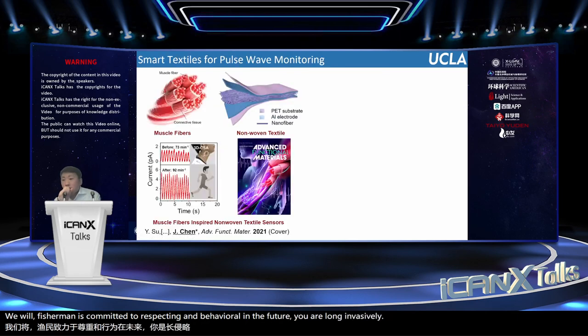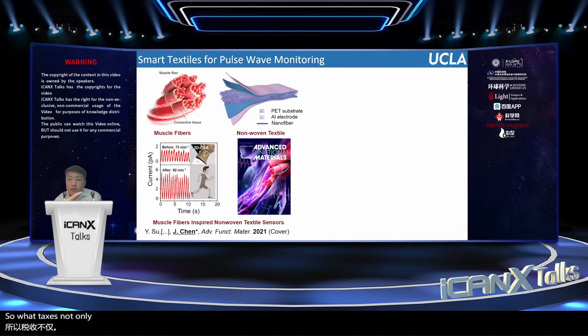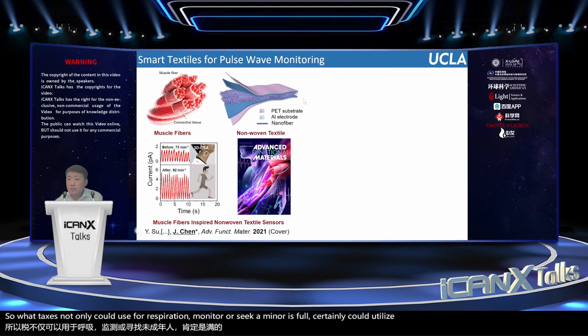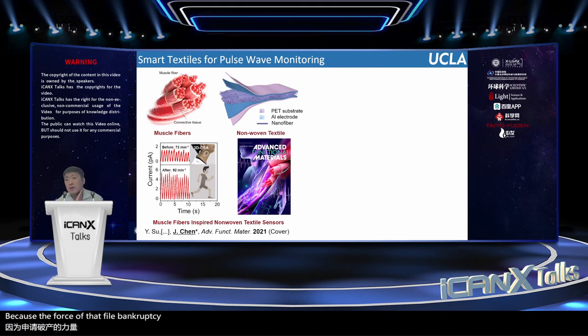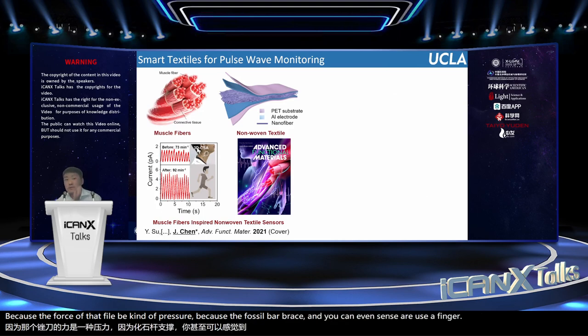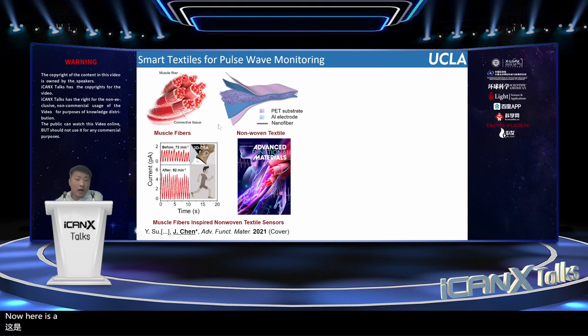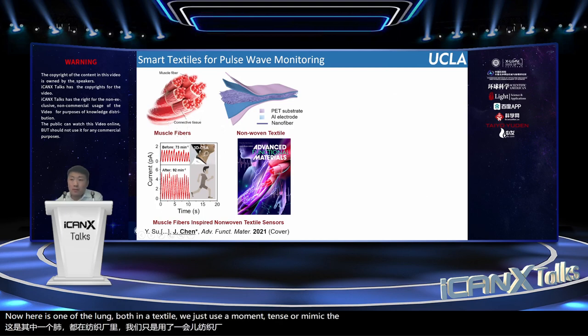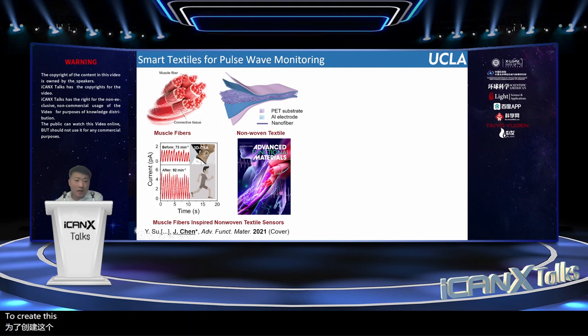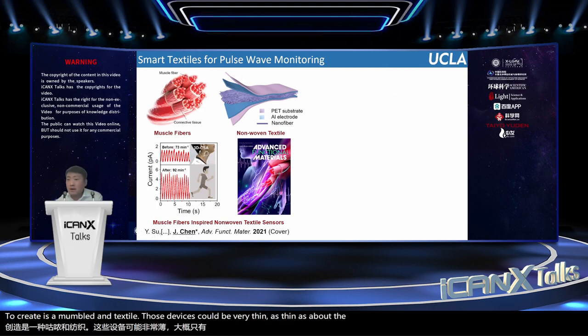For textiles, not only can we use them for respiration or sleep monitoring, we can certainly also use them for pulse monitoring, because the pulse has a lot of biomechanical pressure due to pulse vibration. You can even sense it with the fingertips. Here is one of the non-woven textiles. We used a non-woven textile to mimic muscle fibers. Those devices can be very thin, about 70 micrometers.